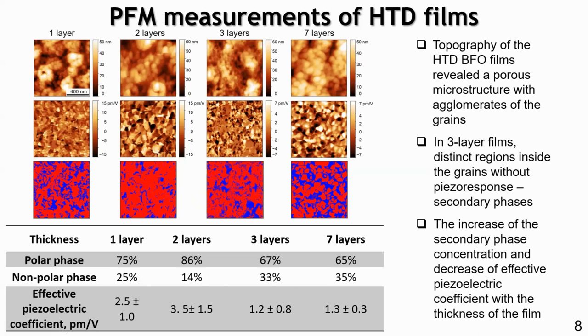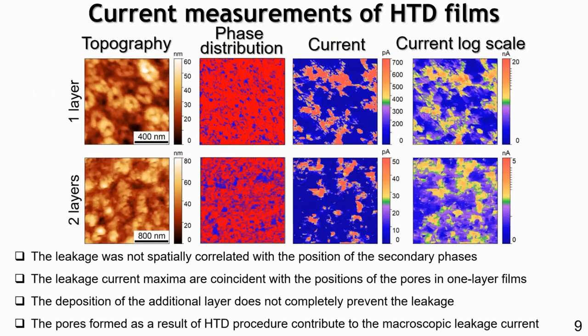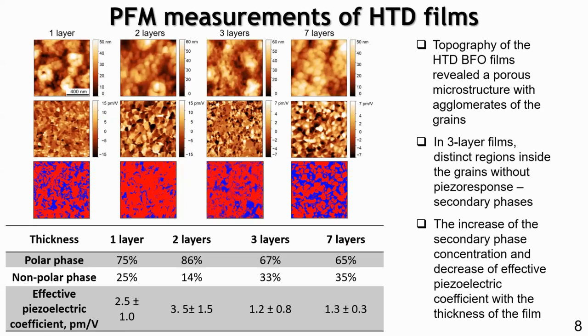Especially, what we also did, we estimated the effective piezoelectric coefficients, and we see that with the increasing number of layers, the effective piezoelectric coefficient significantly decreases. And it makes sense, so these films are really imperfect. In order to compare these films with other sets which were created with the long time and low temperature drying procedure, if we see these pores, we tried to understand how these pores influence the leakage current, which is a problem of the BFO material.